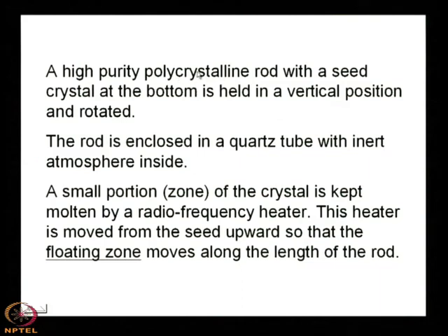Can you remember? We have synthesized very high purity polycrystalline silicon of the order of 10N or 11N purity. So, in almost all the cases, be it Czochralski technique or float zone technique, the starting material is high purity polycrystalline silicon. And here also a high purity polycrystalline rod with a seed crystal.